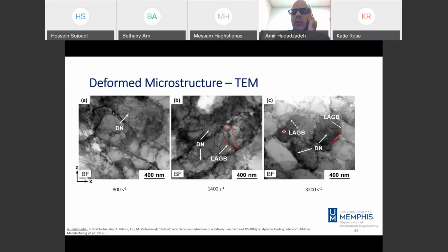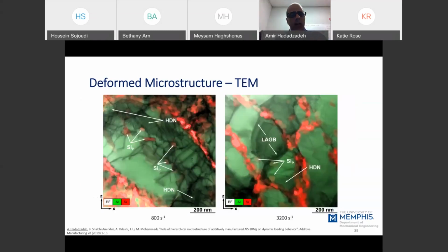At 3200 per second, we have very well developed low angle grain boundaries, and we have the dislocation networks as well. The interaction between dislocations and the features can be seen here. So both silicon precipitates, for example, in this case, and the eutectic silicon walls are playing a significant role in hindering the dislocation and evolution of the dislocation networks. Because the dislocations cannot move easily, they are pinned by the silicon precipitates, as you see here, and also there is another barrier against their movement here.